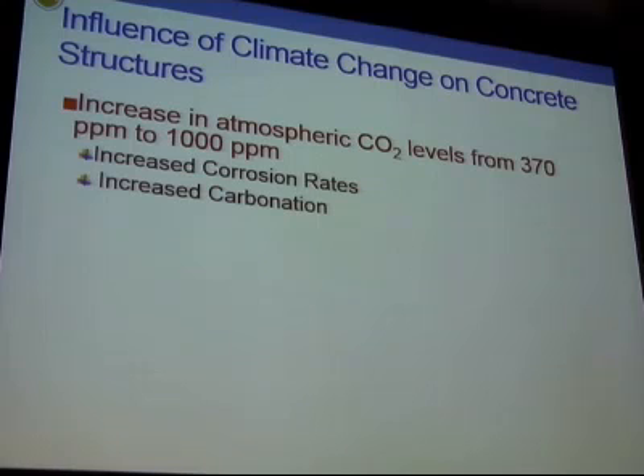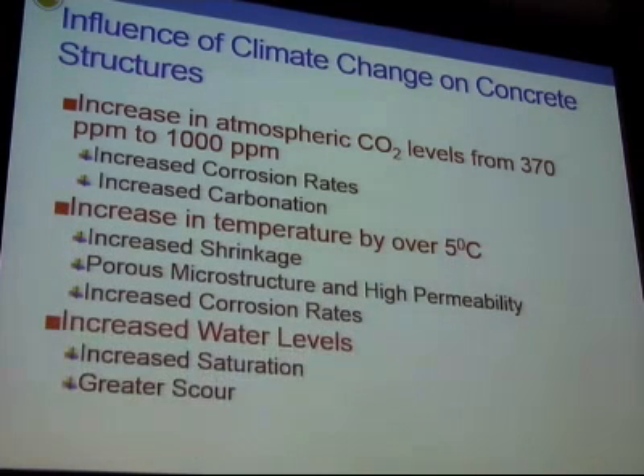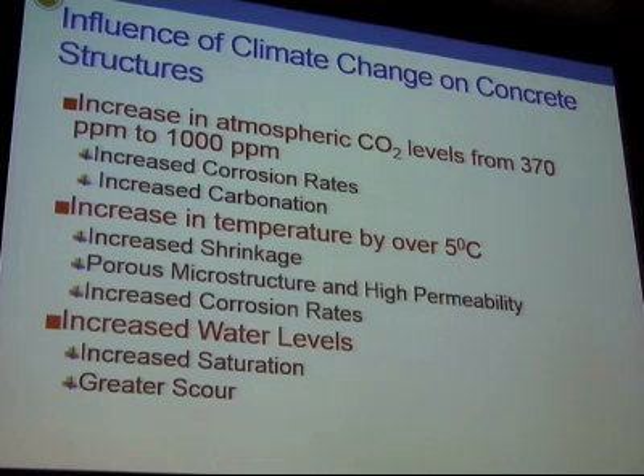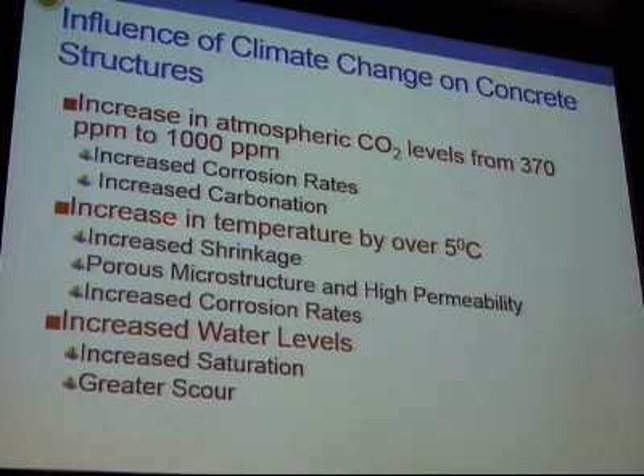And I think to complicate issues further, there is also an issue of global climate change now. We just finished a doctoral thesis here, which looked at, in fact, 7 large cities of the world, including Shanghai, and how the global climate change will affect our concrete structures. So if you look at our concrete structures, and now at the increase in atmospheric CO2 levels from 370 to 1,000 ppm, which is what scenario 4 from the IPCC tells you, you would definitely get an increased corrosion rate. You would get increased carbonation, which causes corrosion, as you know.